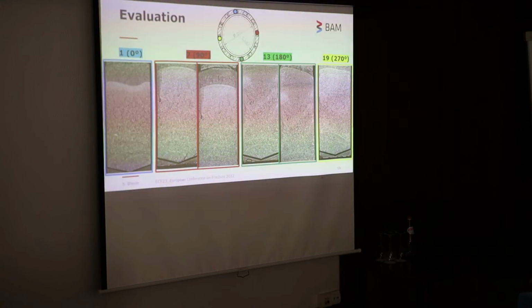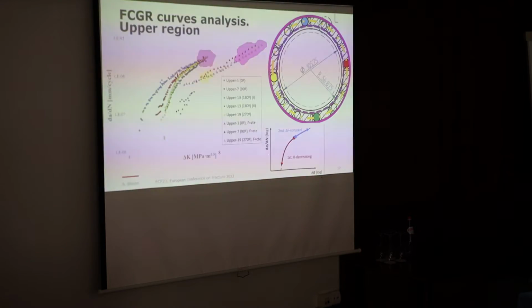And first of all, I would like to show you the images of the fracture surface, because especially in the case of the 0 degrees, we can see some effects probably due to the residual stresses. And it's easy to see these effects when we compare the results from the different points that we are evaluating. For example, if we compare the 0 degrees against the rest of the positions, we can see clearly some kind of effect, probably due to the residual stresses. Also, an important highlight is that when we compare the behavior of the material at different positions in terms of the thickness, we can see differences, because there is some kind of mismatch under the same loading conditions. So that basically lets us know that it's difficult to manage this kind of material.